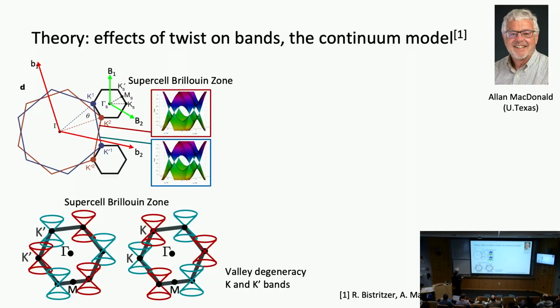So here's what happens. I mentioned that there's a hexagonal Brillouin zone in one graphene layer. Well, with 2 graphene layers, you have 2 hexagonal Brillouin zones. The blue one is from the top layer and the red one is from the bottom layer. And at each corner of these Brillouin zones of each individual graphene layer, you would have a set of Dirac cones, just like I showed you a moment ago for an individual graphene layer. But because of the Moiré periodicity, the Moiré superlattice, you would have now a supercell Brillouin zone in reciprocal space, which is this one outlined by black. So that is the Brillouin zone of the Moiré scale.